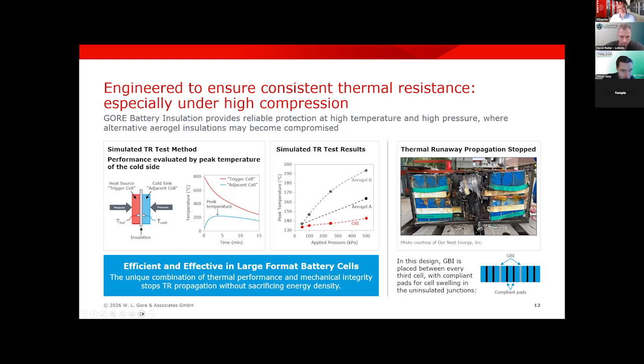So the material provides really the reliable protection on high temperatures. What you see here is a heat and trigger cell that is applying temperature. You're putting the insulation material in between and have a cold sink and the adjacent cell where you could measure the temperature too. And what you see, the temperature peak is not going higher when you use the right material. But the most interesting thing is if you compare it under applied pressure.